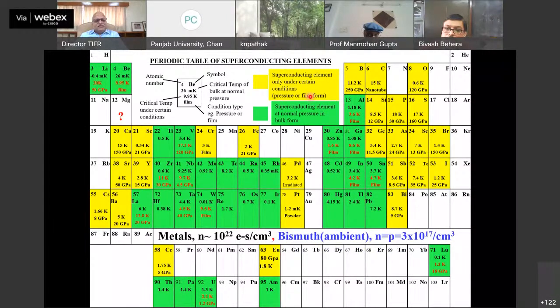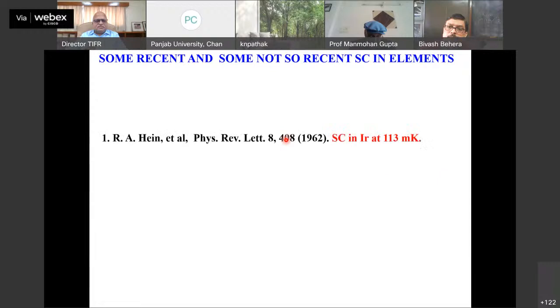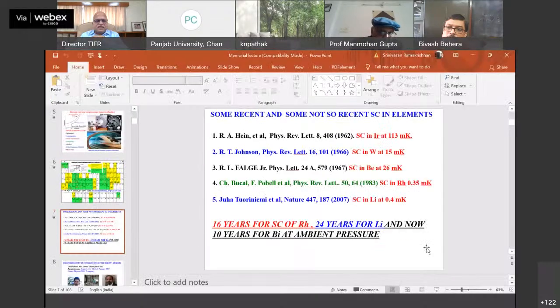Most of the metals have a very high carrier concentration, of the order of 10 to the power of 22 electrons per cubic centimeter. Bismuth is a unique element because it has a carrier concentration 5 orders of magnitude less than the typical metal. It is also called a compensated semi-metal.